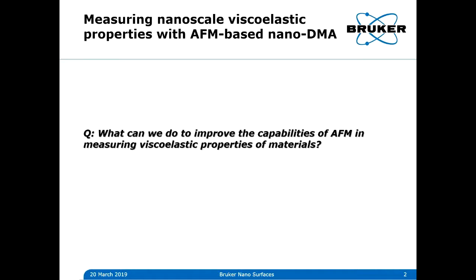The first one is really that rheologists need to measure the storage and loss modulus at multiple frequencies and multiple temperatures to completely characterize their polymer behavior. Additionally, they are accustomed to using the bulk DMA to analyze their samples. So direct comparison with the previous results that they've collected requires low frequencies. That's typically under 100 hertz. So we've been working with several different collaborators, and additionally our colleagues at Hysitron, which is now part of Bruker, to fill this gap by developing a new mode for our Dimension Icon AFMs. And this mode is the AFM-nDMA that Dalia mentioned.